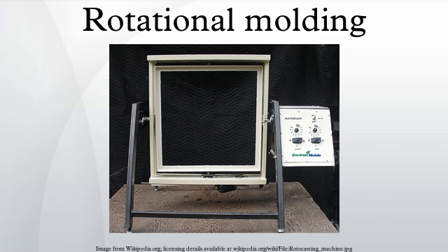The rotational molding process consists of 4 distinct phases. Loading: a measured quantity of polymer is loaded into the mold. Heating: the mold is heated in an oven while it rotates, until all the polymer has melted and adhered to the mold wall. The hollow part should be rotated through 2 or more axes, rotating at different speeds, in order to avoid the accumulation of polymer powder. The length of time the mold spends in the oven is critical.